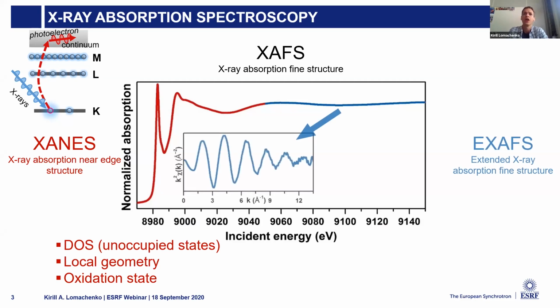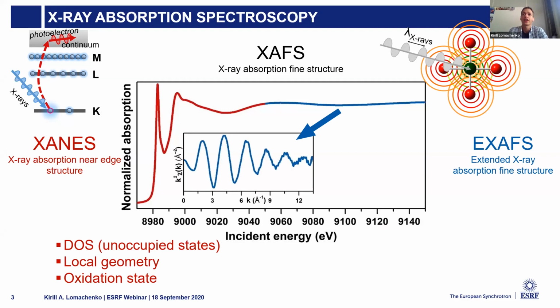The other part, further away from the absorption edge, is called extended X-ray absorption fine structure, which is basically an interference pattern created due to the interaction of the photoelectron wave outgoing from the absorbing atom with the same wave backscattered from the neighbors.